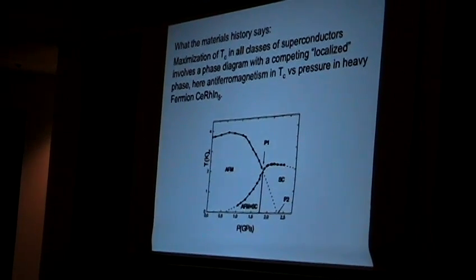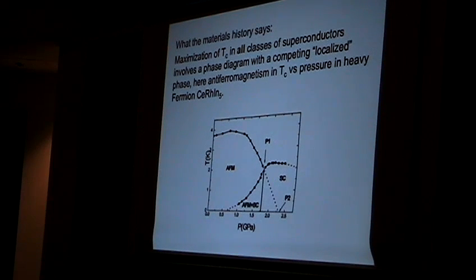If you look at the whole history of superconducting materials, the earliest phenomenon was regarded as very rare. And in fact, as time went on, we found out that superconductors are all over the place. The only systematic that was ever discovered, to my knowledge, before heavy fermions was the so-called Matthias rules, which really only applied to transition metal alloys. There were certain electron per atom ratios where transition metal alloys peaked in their